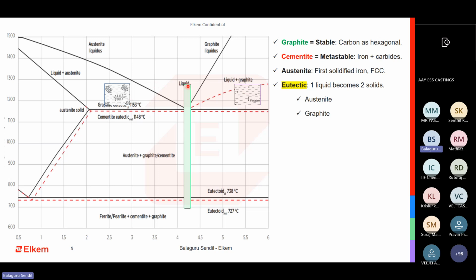So if you are having your base metal with the correct chemical composition, and if the transformation is happening at eutectic, you have both the austenite and graphite growing parallelly. If you are on the hypo side, you have first the austenite growing. If it is on the hyper side where the carbon is more, then first the graphite comes out. It is not the austenite. This is very important to understand, because it influences how the casting is solidified and the graphite management. And hypereutectic cast irons require a different kind of risering system and a different kind of inoculation practice when compared to a hypo or eutectic.